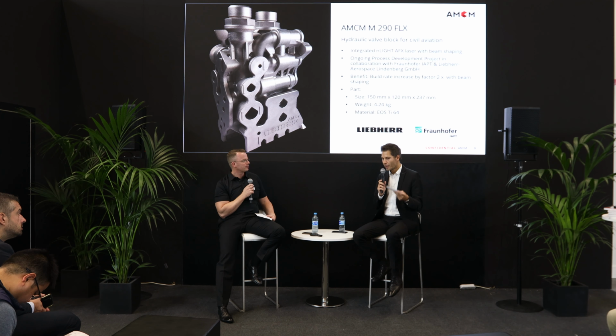So productivity is one. The second one is process stability, which I already mentioned. Third one is that you can directly influence the microstructure in these areas where you want to have it, because the different melt pools and the different melt pool behaviors lead to different effects with regard to the microstructure. So you have different cooling effects and therefore also resulting different microstructure. This is a very, very good possibility of influencing it. You can also have different overhangs by using beam shapes, because the energy input is not that deep. You're not having like a keyhole welding process anymore. It's more flat, the melt pools, and therefore you can also get rid of some surfaces based on the staircase effect and so on.